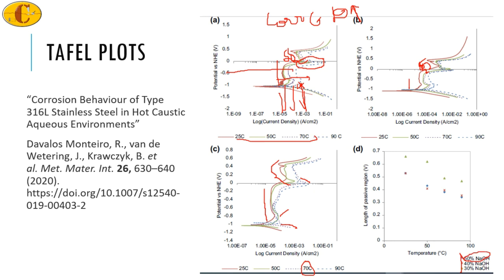Only then you will be able to match or estimate the reason why we should not use carbon steel in a particular environment. What is the reason that if we do use stainless steel, what should be the thickness of the material of stainless steel or of the component? We can match the service chart values to these kind of Tafel plots and Pourbaix diagrams to get a more accurate estimate and design the components accordingly.